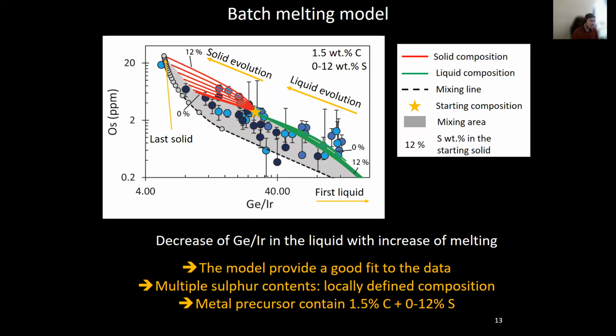So you have here an example of our model. We report the osmium, again, the germanium to iridium ratio. You have in red the solid composition, in green the liquid composition, and the yellow star is the starting composition. The area in gray is the range of compositions that can be made by mixing a solid and a liquid. The blue points on the diagram are our results.